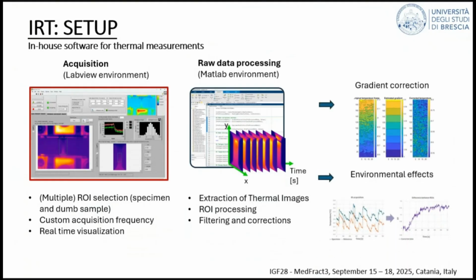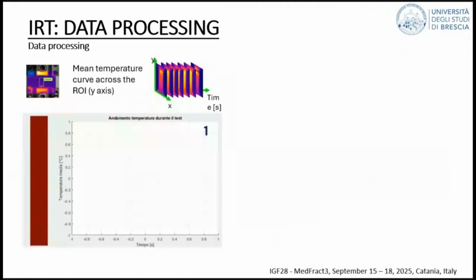In particular, two corrections. One is that when we pointed the camera at the equipment, we found there was a slight mismatch in temperature between the upper and the lower grip. It's not much in terms of Celsius degrees, but you will see that in some cases the temperature variations that we measured were very small. So we corrected for this gradient and for environmental effects when necessary.